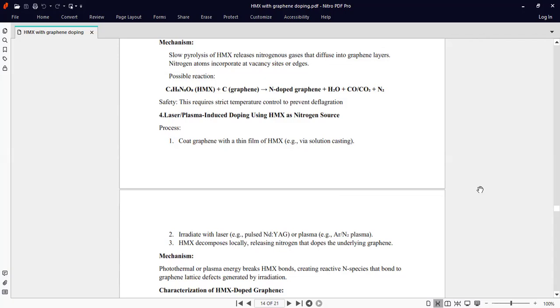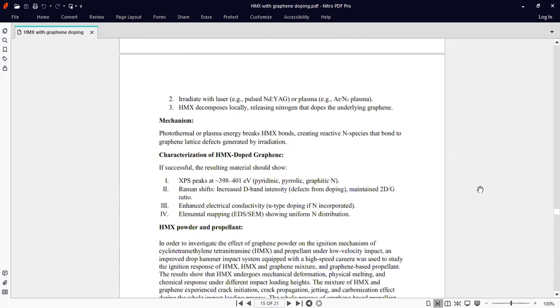Laser plasma induced doping using HMX as a nitrogen source. The process is to coat graphene with a thin layer of HMX via solution casting, then irradiate with a pulsed Nd:YAG laser or plasma. HMX decomposes locally, releasing nitrogen that dopes the underlying graphene.